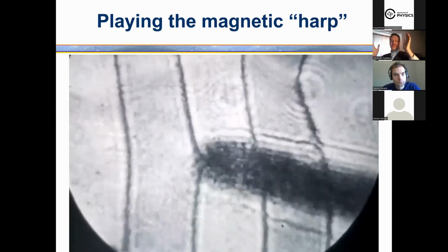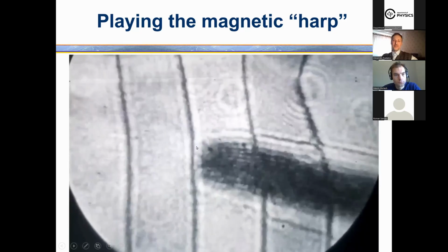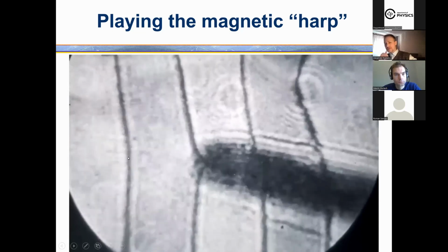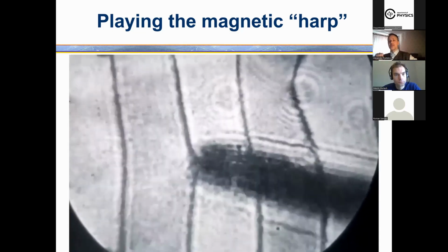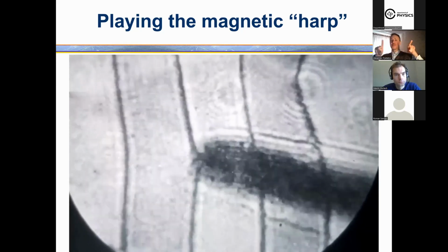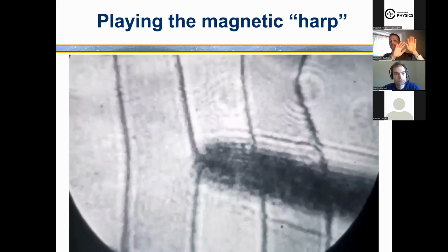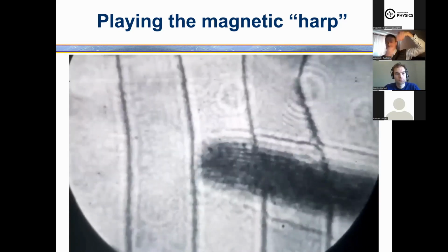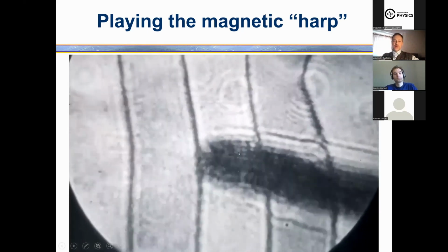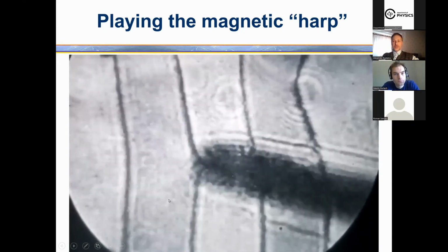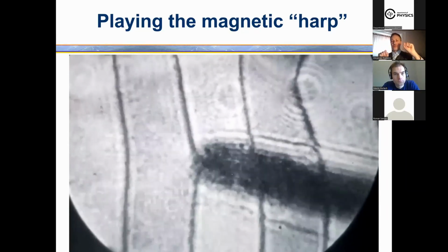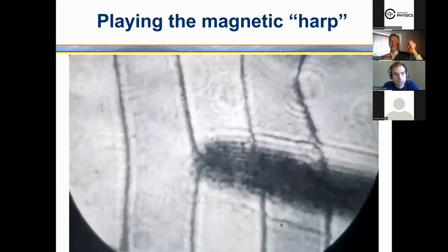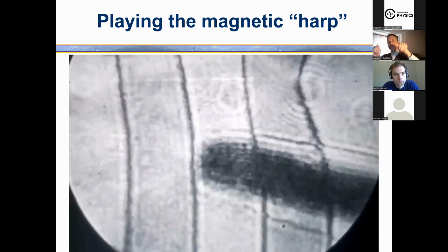Because the equilibrium positions are dictated by magnetostatic forces, and you should move all the domain walls. So it may be possible, but you need multiple electrodes and some kind of grid, or maybe an interdigitated electrode system to transform it. And desirably, there should be some kind of defects to pin the domain walls to a new equilibrium position, so they can be transferred from one pinning site to another pinning site, like this.